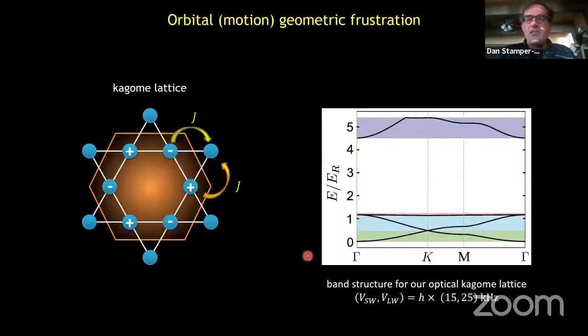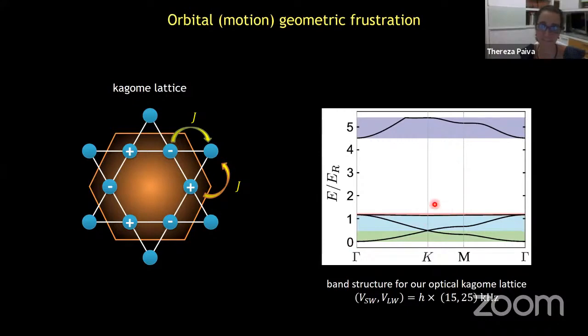So, for example, looking at this band structure, the flat band in the Kagome lattice, as I spoke about briefly, is the third band of the Kagome lattice. And we've been studying the dispersion relation in the Kagome lattice in a very non-equilibrium setting. We take a whole gas of atoms, we put it entirely into the highest band, highest S band of the lattice. That's not a stable situation. But we wanted to study flat band physics, but we wanted to do so in a more stable situation. Working with fermions is a much smarter approach. We can now just put in enough fermions so that the Fermi energy is in the flat band. That's it. And then everything becomes interesting.